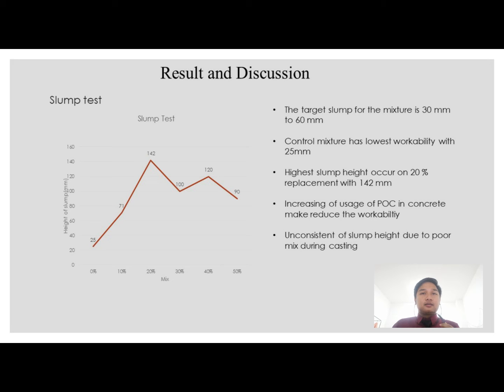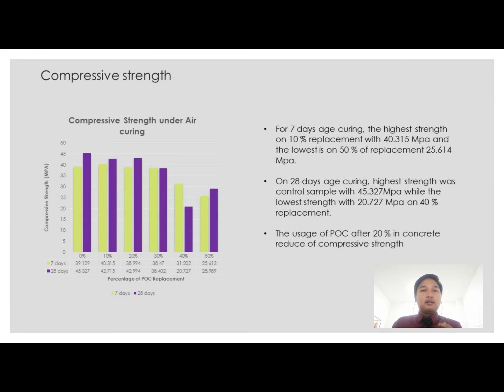For the compressive strength, this is under air curing. For 7-day air curing, the highest strength is at 10% replacement with 40.35 MPa, and the lowest is at 50% replacement with 25.614 MPa. On 28 days air curing, the highest strength is the control sample with 45.32 MPa, while the lowest strength is 20.727 MPa at 40% replacement. The usage of POC after 20% replacement in the concrete can reduce the compressive strength.